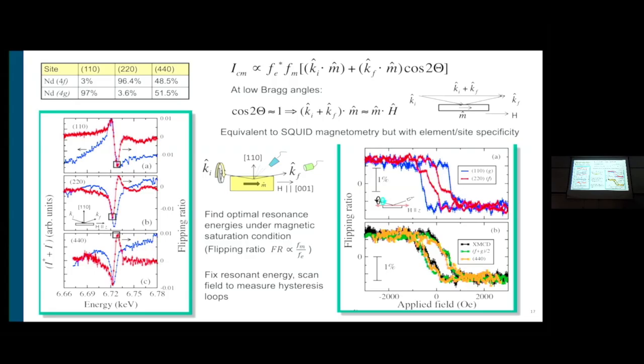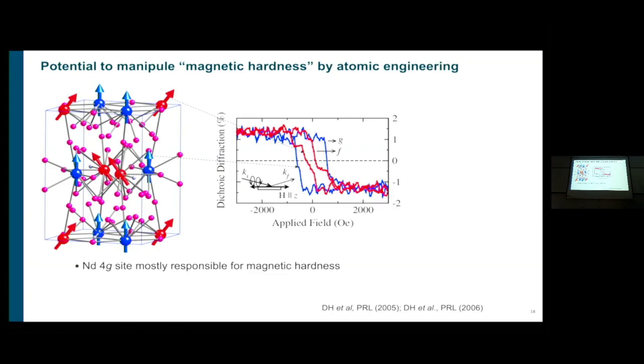So this is, of course, very important because it tells you that in this structure, only one type of neodymium sites is contributing the most to the magnetocrystalline anisotropy. So if you can figure out how to replace the other site and put a different type of rare earth there, or do some other trick, even put in a gadolinium atom that is isotropic and it doesn't compete with the other anisotropy, maybe you can get a better magnet.